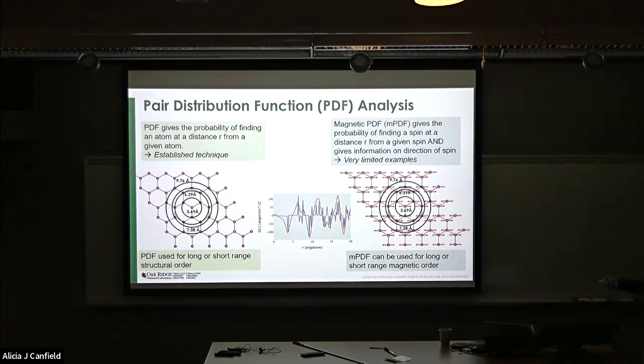So this is showing, I'll just kind of explain what this plot is. So if you consider your central atom with this spin here, if you go out, the nearest neighbor is 3.69 angstroms away. And then if you get this PDF pattern, you would expect to see a peak at 3.69, and this is what you see. And then if you go out to the next nearest neighbor, it's 6.4 angstroms away. Down here, you get another peak, and you go on, and then you can fill out your pattern. And this is firstly a model independent way just to look at what's happening in your structure, and then you can start to fit this.